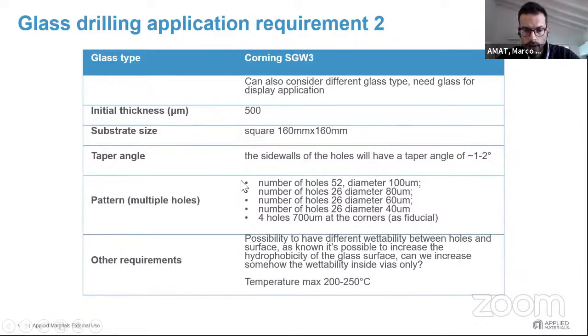We are currently doing some sampling for this customer. And we have a specific layout of an array of holes with variable diameter. Pretty much the same requirements as before, plus, in this case, 4 holes at the corners with 700 microns. And here there is also an added requirement in our wish list, which is about tweaking a little bit the surface behavior where we process with the laser.